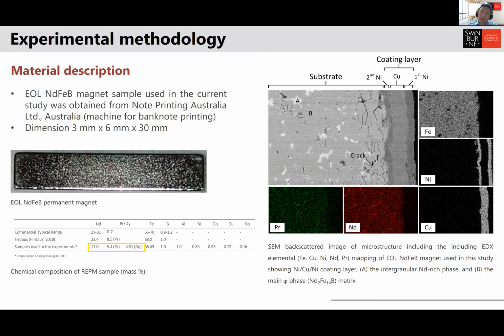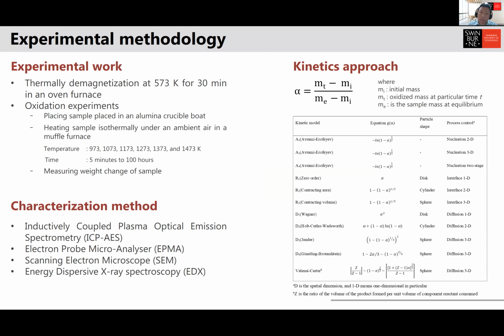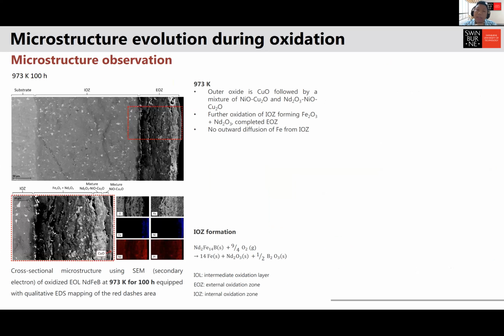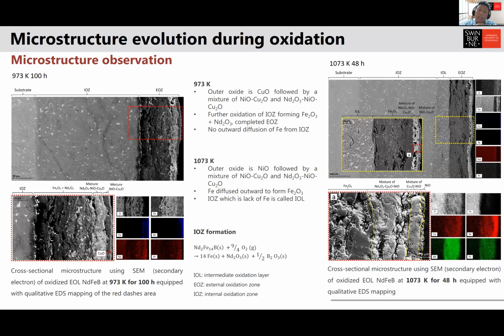So we do oxidation study and also do some kinetics analysis. I won't go into the detail, but that's just want to mention in there. And then we study the microstructure, right? What we found is that when we have some coatings, it has a strong effect, first of all, on the microstructure evolution, as well as on the kinetic itself. So at different temperature, we also find different microstructure evolution, right?